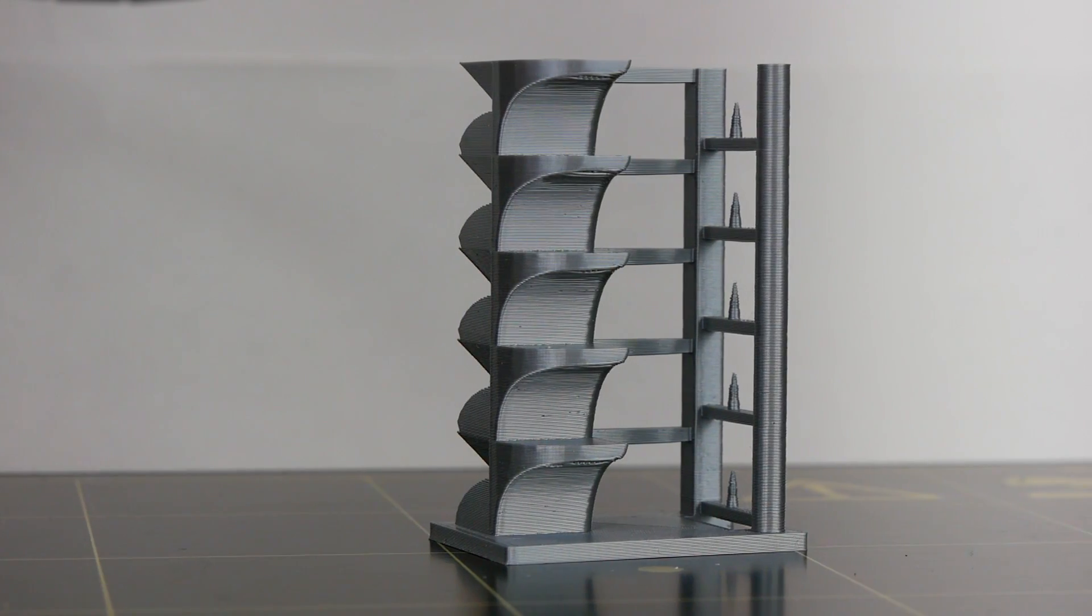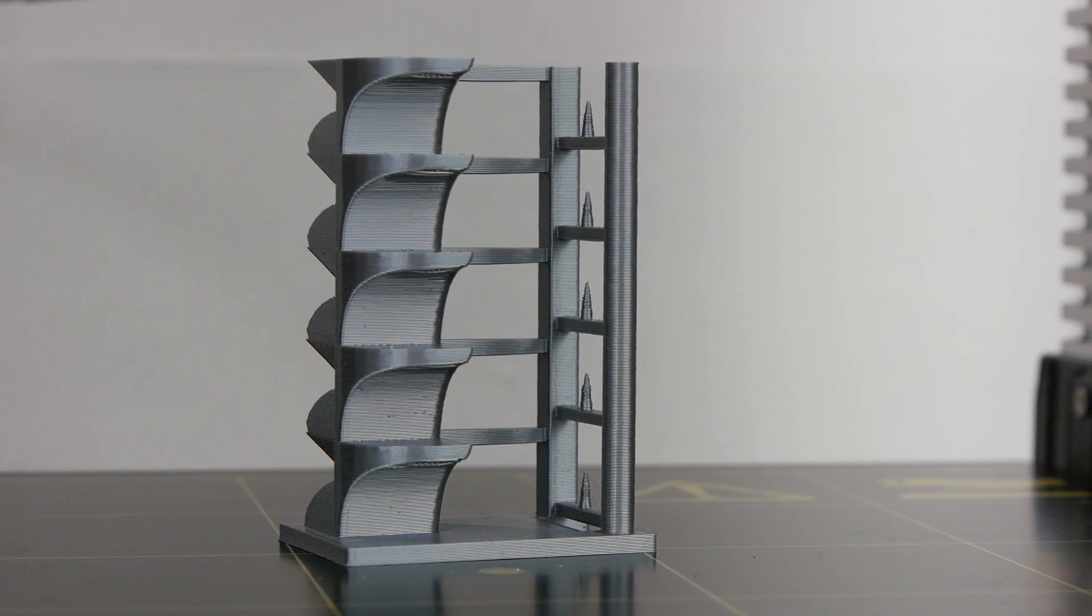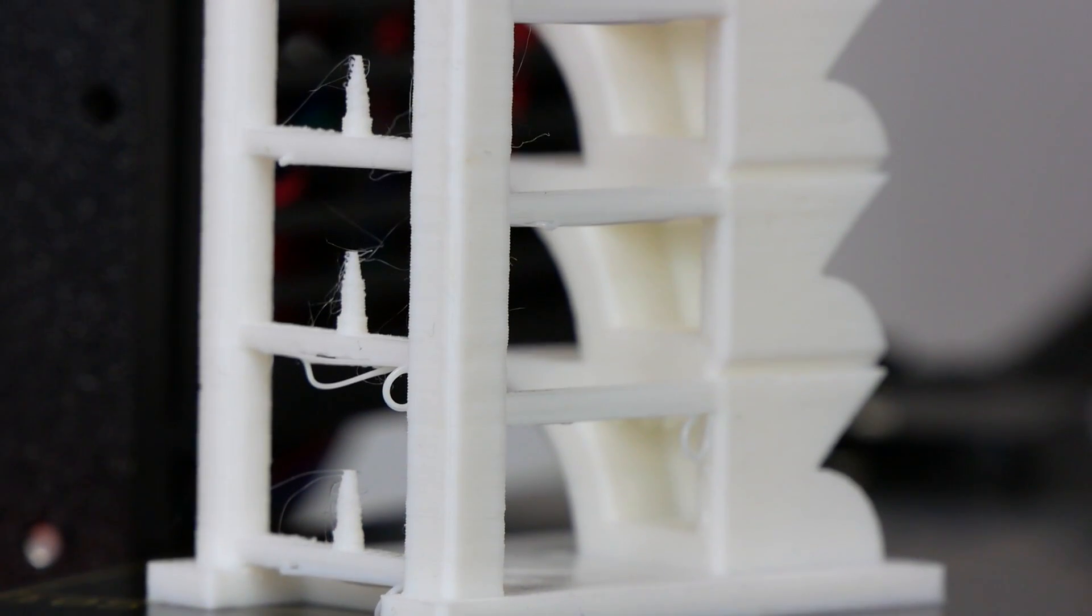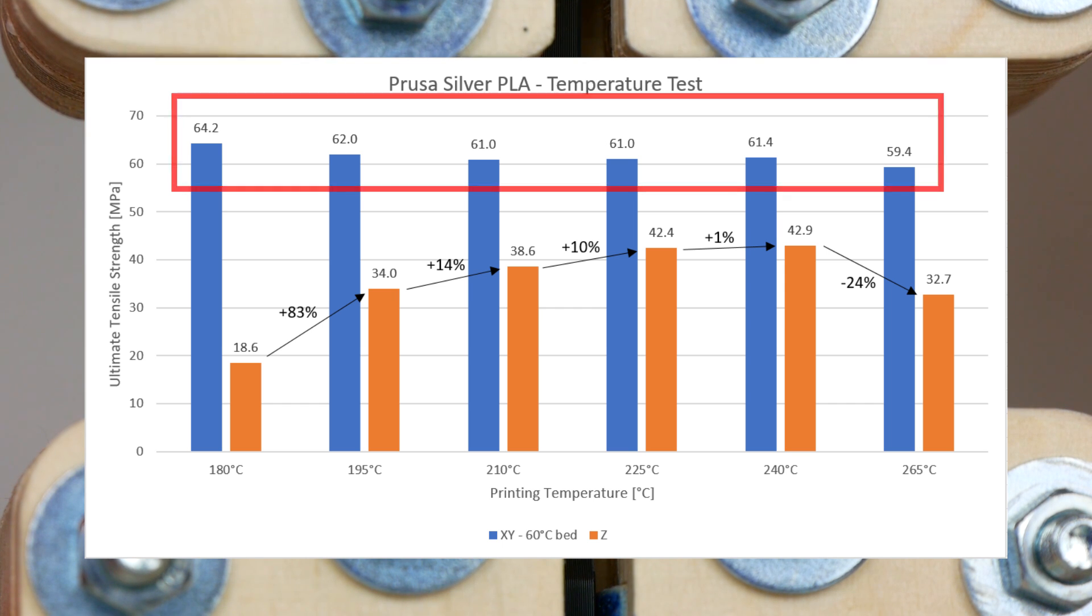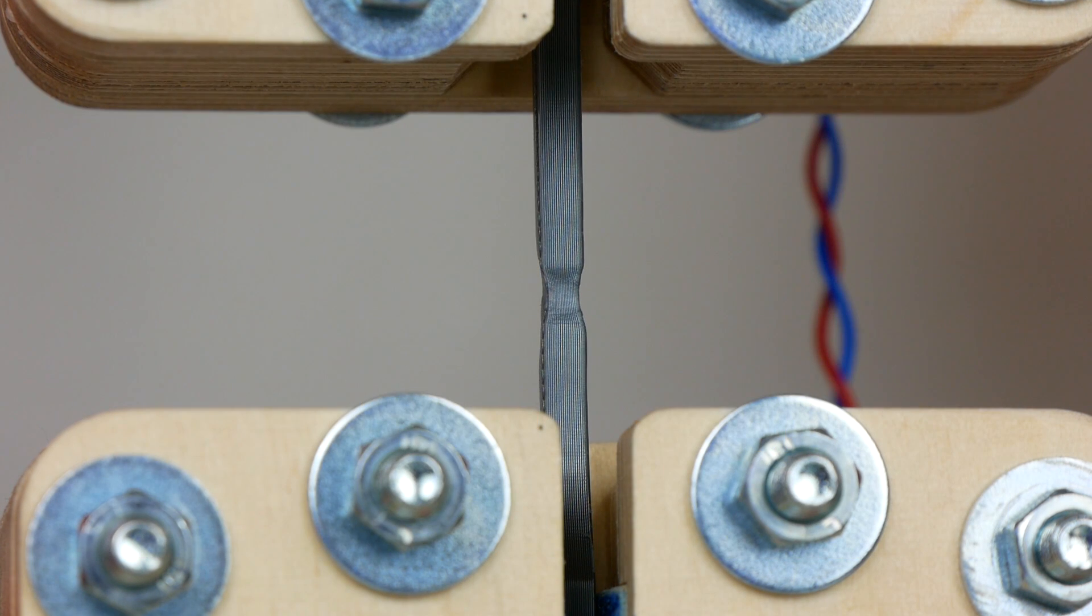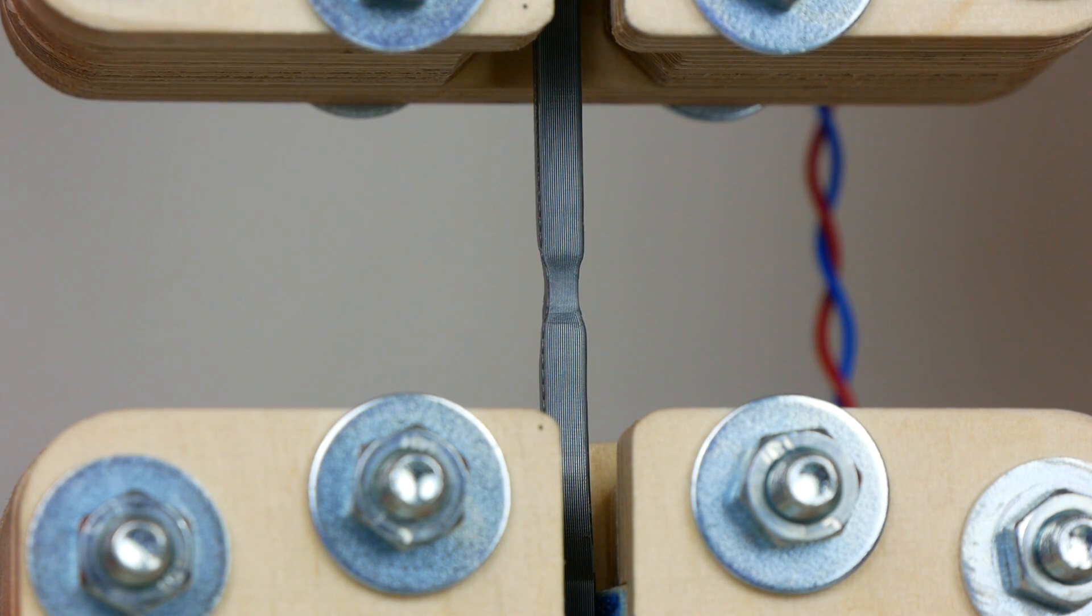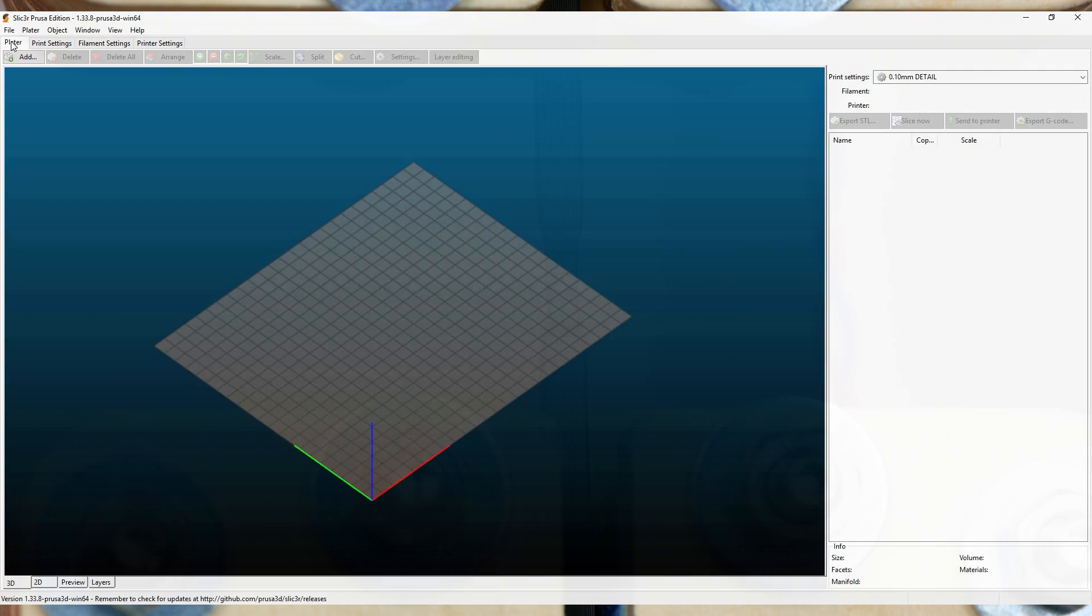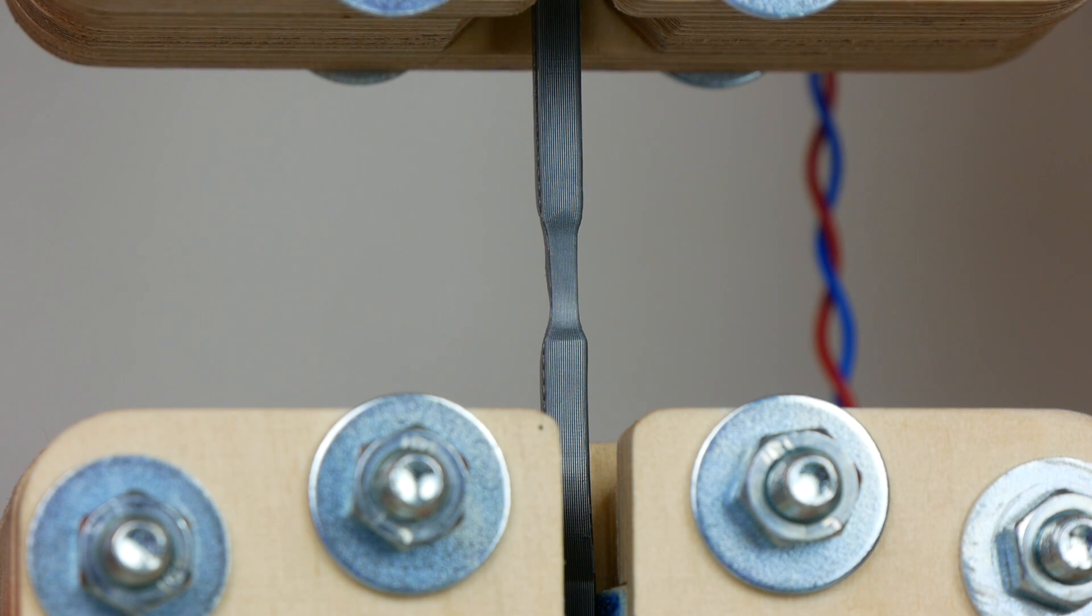So we have seen that Prusa's PLA is usable in a quite vast temperature range and doesn't start to degenerate before 250 degrees. This is not true for all PLAs, because for example BQ's PLA had to be printed at much lower temperatures. The bulk strength of the lying specimens wasn't greatly affected by the print temperature, but the layer adhesion constantly increased up to the point where the material started to degenerate. So if you want to get better layer adhesion, increase your printing temperature maybe a little bit. The default printing temperature in Prusa Slicer edition is 205 degrees, for example. Looking at these results I would increase the value to around 220 degrees because I have seen that the print quality stays the same but the layer adhesion is a little bit better, which is good for parts which are mechanically loaded.